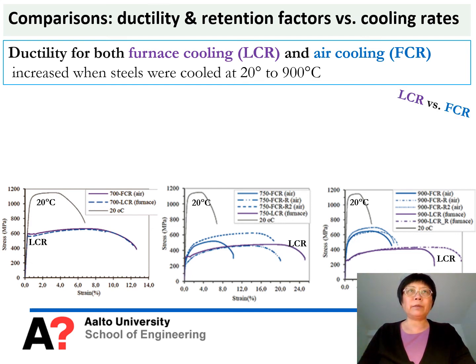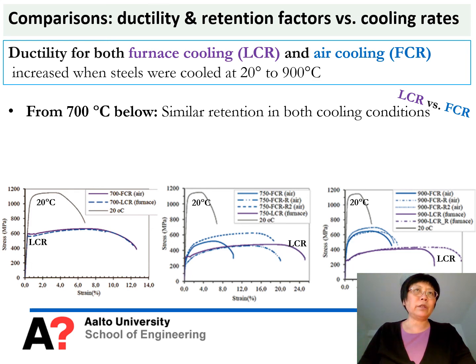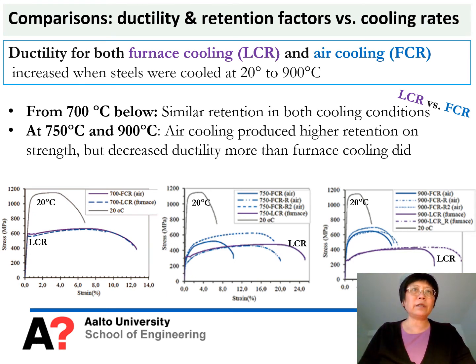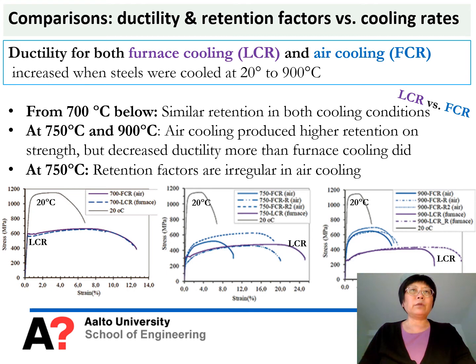And when comparing both cooling methods, it can be seen that when the steel was cooled from 700 and below, similar retention was observed in both cooling conditions, and also between 750 and 900 degrees. Basically, air cooling produces higher retention of strength, but decreases ductility more than furnace cooling does. And at 750, retention factors are irregular in air cooling, as can be seen from the stress-strain curve in the middle.